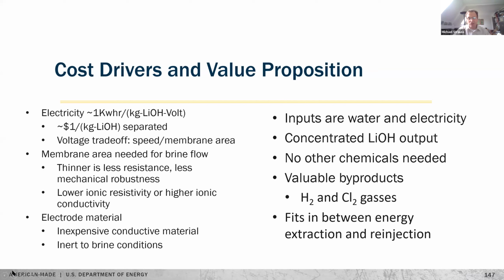I'll show this fundamental trade-off later. The membrane itself has its own trade-offs. Thinner is better, less resistance. But you want enough thickness so that you've got mechanical robustness. So that's another fundamental trade-off. Higher conductivity is better, and so you want high temperature. If you said you want to do this at 800, we would say fantastic, but we're doing it at 100. The electrode material needs to be inexpensive and inert to the hot brine. And we see this whole thing fitting in between the energy extraction and the brine re-injection. Next slide, please.